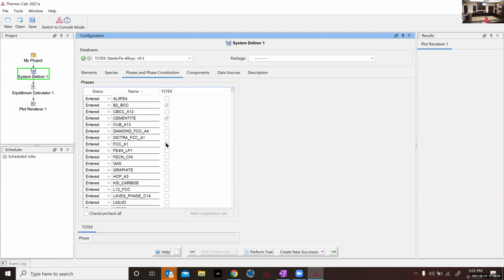So the difference is, I don't think there's really any difference in the iron database, but in the nickel database, just like the BCC B2, the FCC L12, which is the gamma prime phase in nickel-based alloys, are described by the same type of model, an ordering model. But DICTRA doesn't handle the ordering. So if you want to do diffusion in the FCC phase in nickel, you may have to choose DICTRA FCC. But we're going to choose FCC.